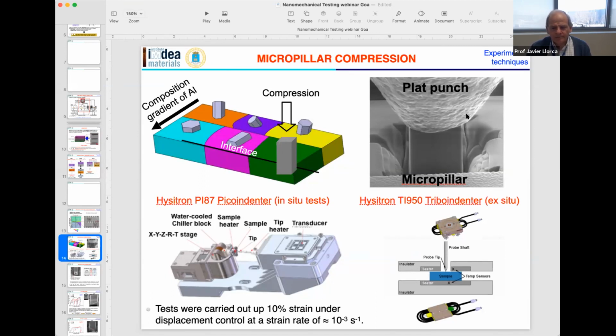This is the micropillar. This is the nanoindenter with a diamond flat punch. And in these investigations, we have used two different nanoindenters. One of them is a Hysitron PI87 PicoIndenter. We have used this nanoindenter within a scanning electron microscope, so you can see in situ the deformation of the material. And we have also used a Hysitron TI950 TriboIndenter, and this is to carry out the ex situ tests. In both of them, we can do tests up to high temperature.